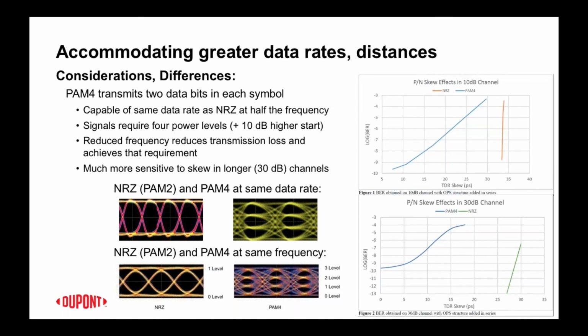In the case of PAM4 comparison to NRZ, the couple of pictures in the bottom left show how at the same frequency of PAM4, you can infer that that's going to get you actually to twice the data rate, whereas the first set of pictures shows PAM4 and PAM2 at the same data rate. And if you notice, the PAM2, the NRZ signal, has twice the number of eyes per time, and so these are all consistent on the time scale.